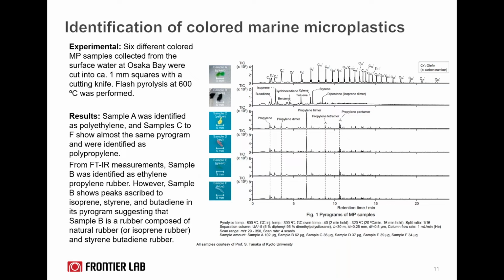So using the F-Search library version 3.6, sample A was identified as polyethylene. How we identified it was by seeing the fragmentation of polyethylene when it breaks down in a random scission manner, and how F-Search identified every pyrolysate to its corresponding polymer. That's how F-Search allowed us to identify those specific pyrolysates as polyethylene for sample A. Then samples C to F showed almost the same pyrogram as you can see here, and they were identified as polypropylene. So they were pretty simple samples because it was just one polymer.